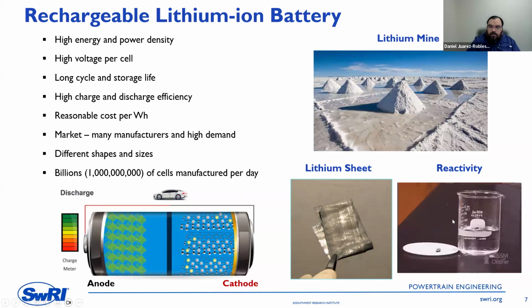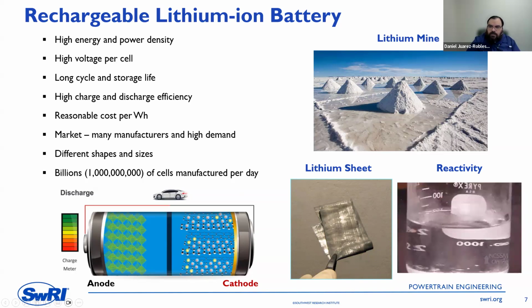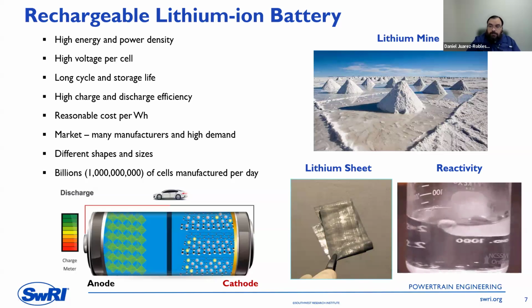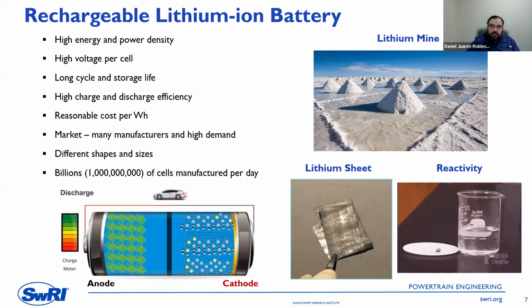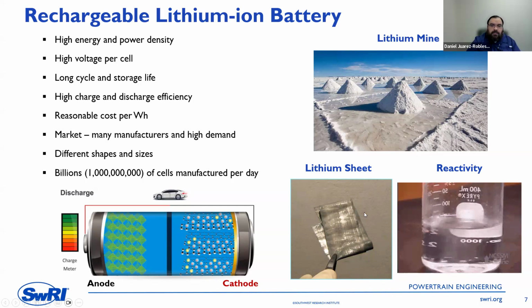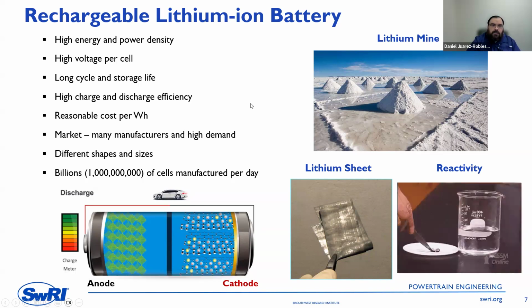And even a small amount of this lithium metal, if you put it in contact with water, has an aggressive reaction. So here is an example. They put maybe a few grams of lithium metal in the water. It starts reacting, and the temperature can rise up to 60 or 70 degrees Celsius in a few seconds. And that was just a small amount. For that reason, instead of using lithium metal in the cell, at the beginning they started using only some cathodes with a limited amount of lithium.